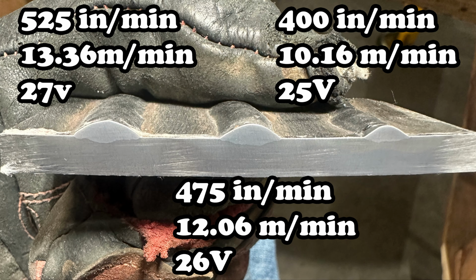Obviously the welds are bigger as you increase wire feed speed, but the penetration really isn't any better going with higher numbers. So at this point I would say the 035 with C25 gas isn't really going to be too suitable for welding 1/4 inch plate. Sure, you can put down big pretty welds with it, but on a fillet weld I'd be highly suspect that you're going to have zero root fusion with this product, which is too bad. But again, I don't think it was ever designed to weld thicker plate, despite the fact it is dual shield.